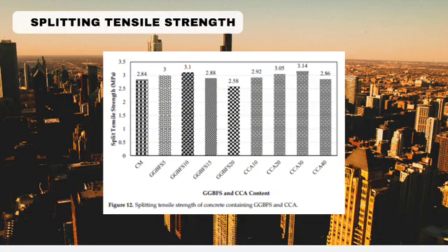Next is splitting tensile strength. This figure illustrates the concrete mixture with 5 to 20% GGBFS by the weight of PC, exploring the splitting tensile strength of concrete. The optimum strength is achieved at 3.10 MPa with 10% of GGBFS, and the minimum strength is 2.58 MPa with 20% of GGBFS at 28 days. The maximum split tensile strength is obtained when using GGBFS as a PC replacement up to 10%. After the further accumulation of GGBFS, the strength declines.